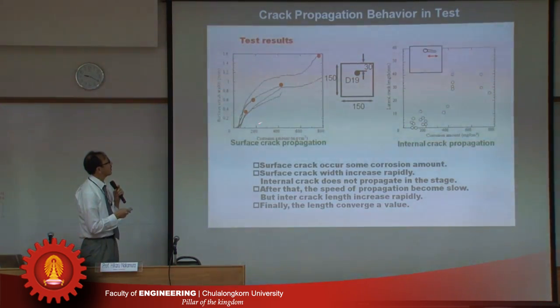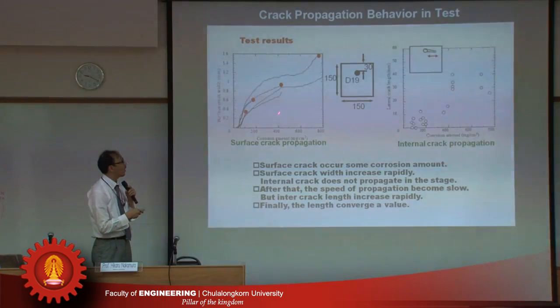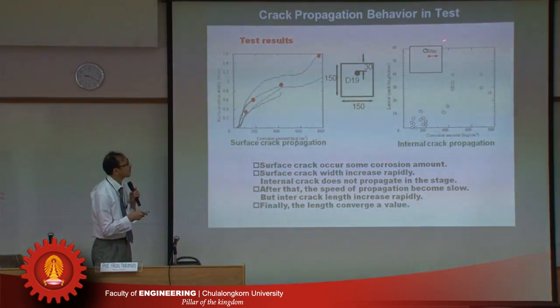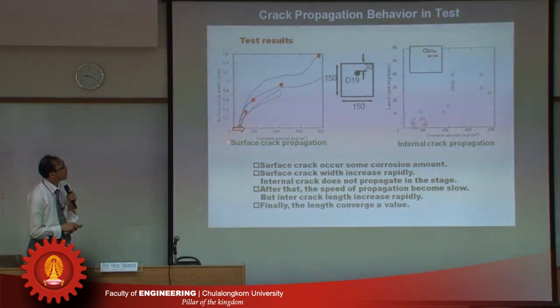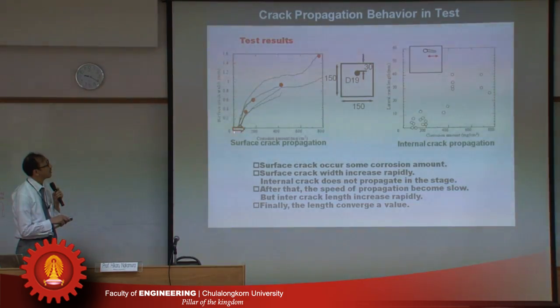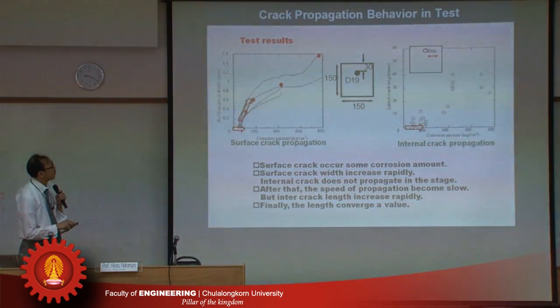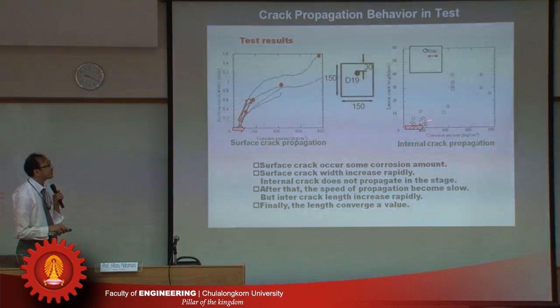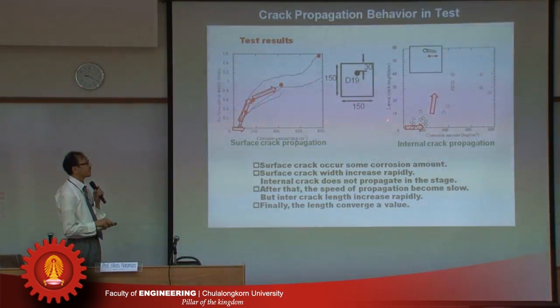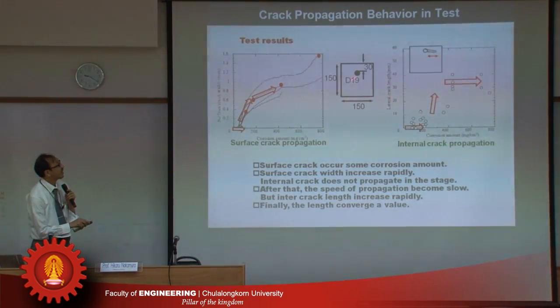So this is one test result. This is the relationship between the corrosion amount and surface crack width, which is the observable information in inspection work from the surface. And this is the internal crack propagation: the relationship between corrosion amount and lateral crack length. In the first stage, a surface crack occurs at some corrosion amount. Next, the surface crack width increases rapidly. However, the internal crack does not propagate in this stage. After that, the speed of the surface crack width increase becomes slow, but the internal crack length increases rapidly. Finally, the length converges.